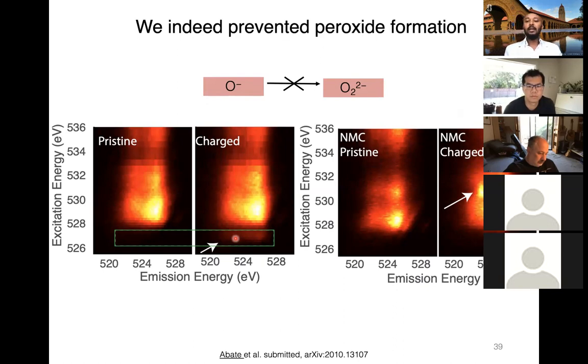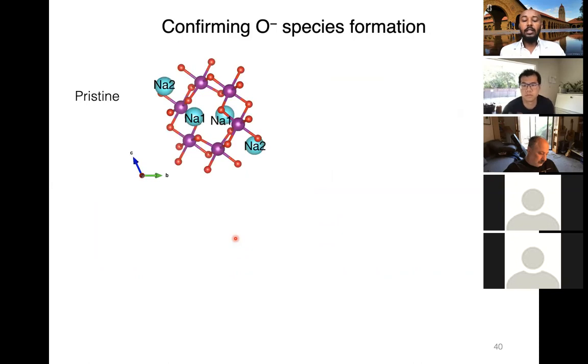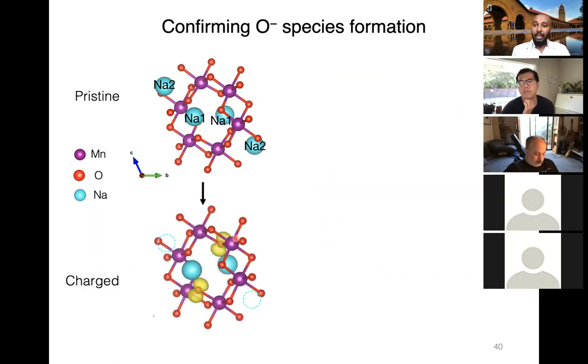To confirm this, I turn to density calculation with my colleagues, where here is the unit cell of the material shown, the manganese, the oxygen, and the sodium atoms in magenta, red, and cyan color respectively. And upon charging, the most important change after removing the sodium atoms is that we are forming these dumbbell-looking structures, which are predicted to be the O- species from the density calculation.